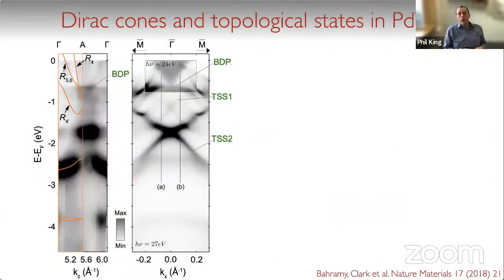And so we can now look for this experimentally. And so I'm showing you on the left here photon energy dependent ARPES measurements, so trying to look at the out of plane dispersions of these states. Now, of course, as photoemission is surface sensitive, we have a rather poor KZ resolution, but you can nonetheless still see some features dispersing down here and crossing at this point just about 600 millivolts or so below the Fermi level. And then you see a small band gap opening up below the next set of crossing points here, then with a larger band gap to a 3D dispersing state down here well below the Fermi level.